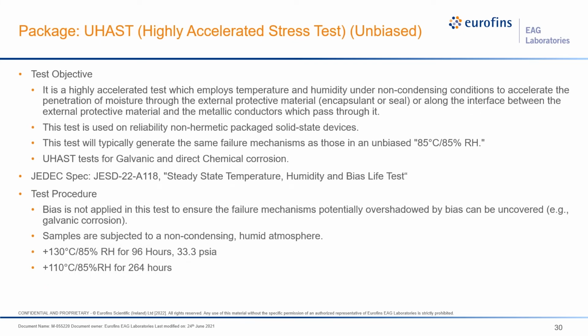Unbiased highly accelerated stress test. This test is done to focus only on the corrosion resistance and package insulation failure modes from temperature and humidity, and not those related to voltage biasing. This test is extremely similar to the biased HAST, except there's no bias here, so there's no concern for power dissipation. The failure mechanisms seen from unbiased tests are corrosion, oxidation, delamination, and not electromigration. Following the unbiased test, you must electrically test it, typically on ATE, to verify that it's fully functional and your device meets all its specifications. Please refer to the JEDEC spec for more information on the unbiased test.